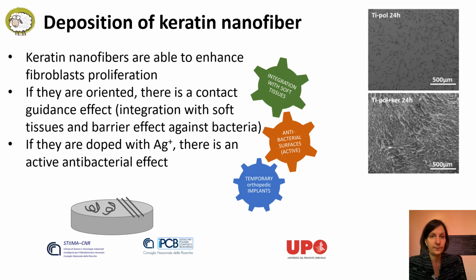Another surface is through deposition of keratin nanofibers. Keratin nanofibers are able to enhance fibroblast proliferation. So again, they are of interest for temporary orthopedic implants in order to enhance the integration with the soft tissues. And again, we can get a contact guidance effect if you have oriented nanofibers. And we can dope these nanofibers with silver ions. So in this case, we can get an active antibacterial effect.